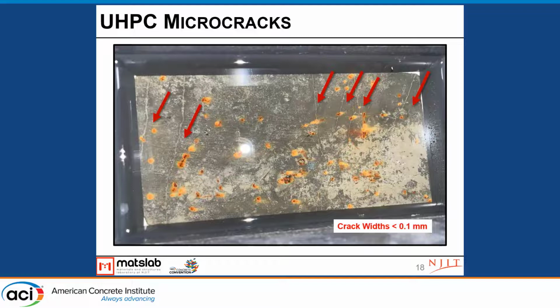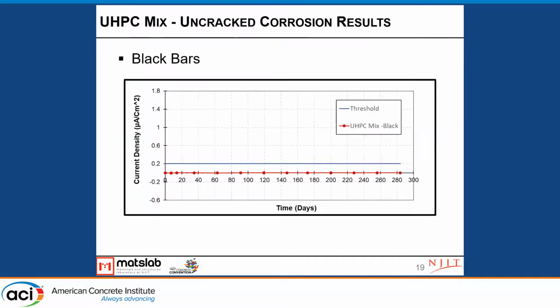Here you can see it after a few months of ponding with salt solution, so you can see some salt in the cracks. But all cracks are less than 0.1 millimeters. That's one of the differences between these materials and normal concrete in corrosion. These cracks can be easily blocked with the salts and some of the corrosion products at the various stages of corrosion happening. And I have a few curves of the results so far.